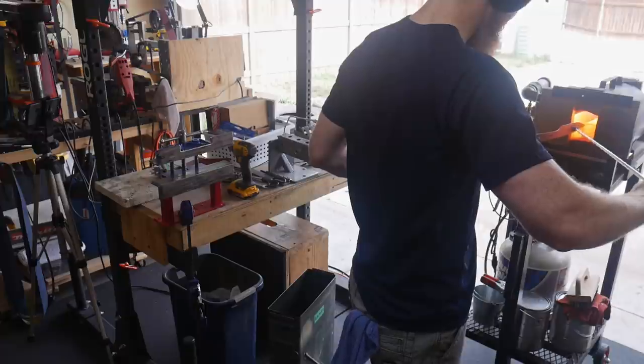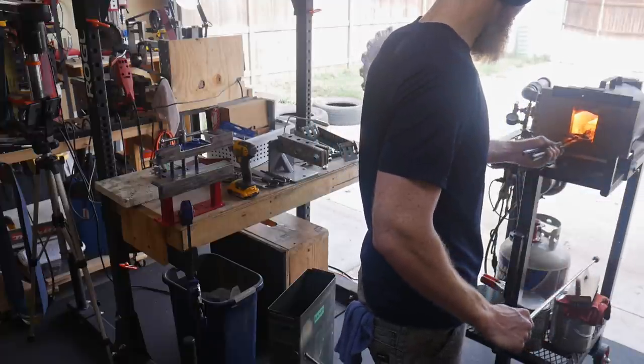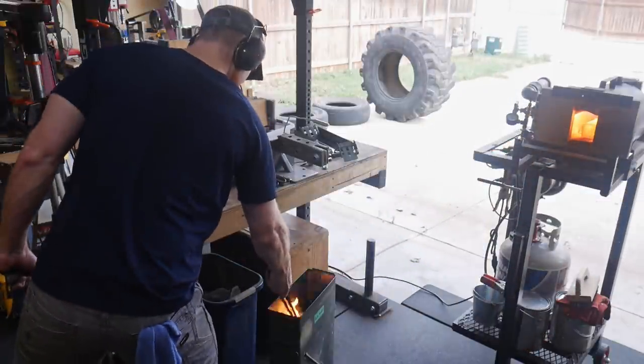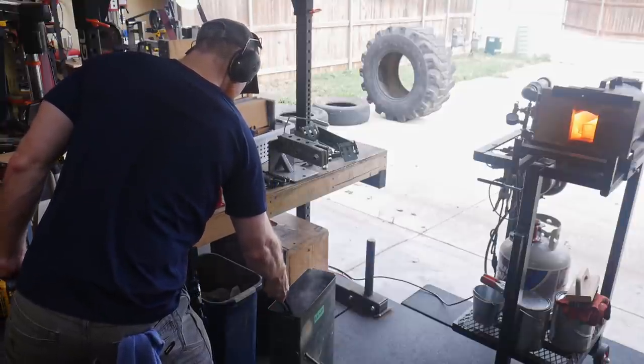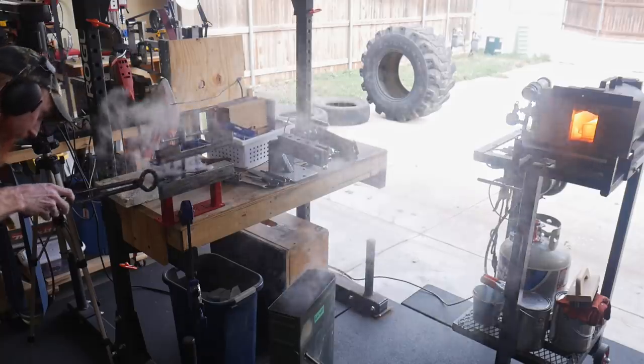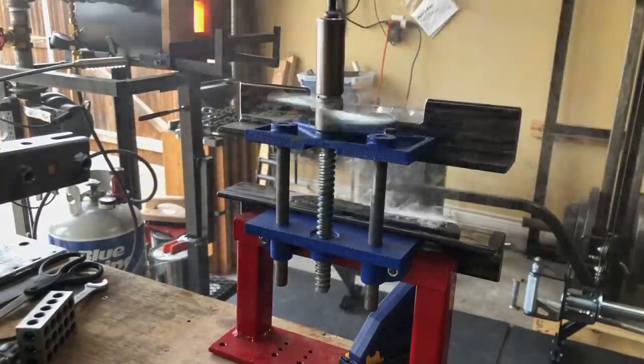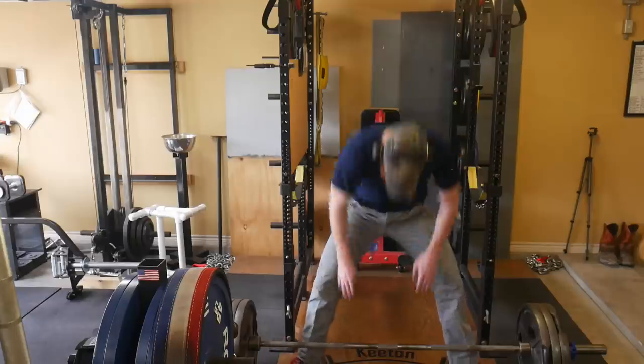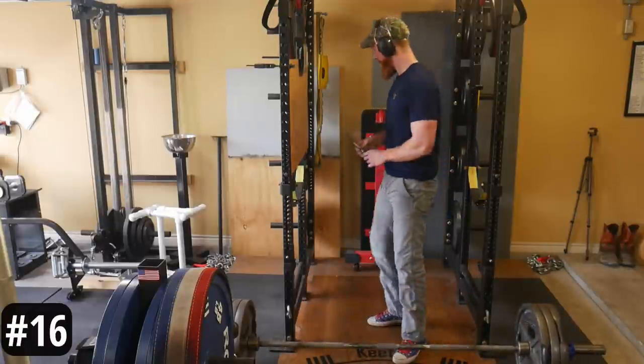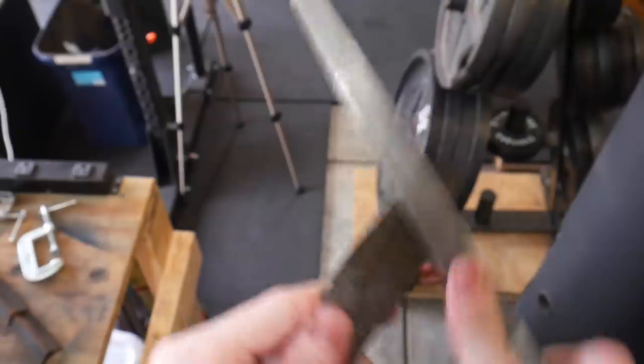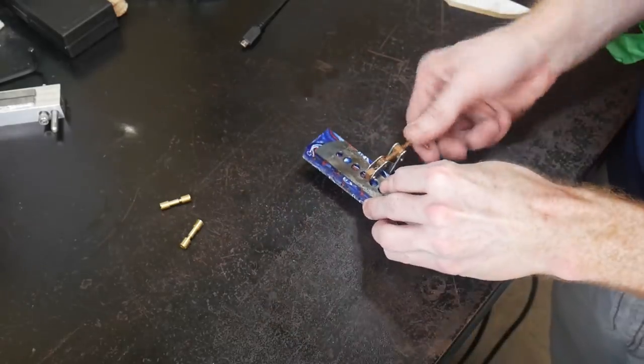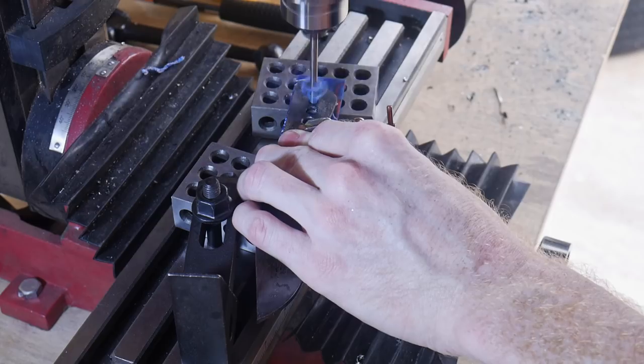So I get the blade up to its quenching temperature, quench it into Parks 50 for about four to five seconds, and then I transfer it to my straightening plates as quickly as I possibly can so that I can clamp this blade straight as it cools. You have a very short window of time to perform this operation on a knife. If you wait too long, the knife could get fully hardened and actually crack during the straightening or holding straight process with those plates.